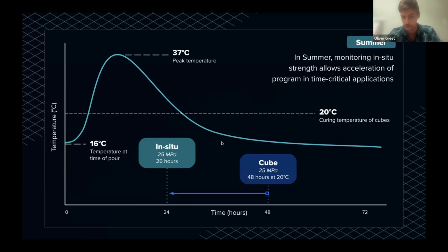So we'll take a summer example here first, and you can see in this case we've poured the concrete at an initial temperature of 16 degrees Celsius, and then due to the thermal mass of the element itself and the exothermicity of the material, that's gained temperature through time. And you can see here it has a peak temperature of 37 degrees Celsius and then cools back off to its environmental condition over time as it loses its exothermal heat to its environment. And you can see here, well, the cube stored at 20 degrees Celsius was actually achieving 25 megapascals in 48 hours. You can see here, actually, due to the elevated curing temperatures, that accelerates for the structure itself.